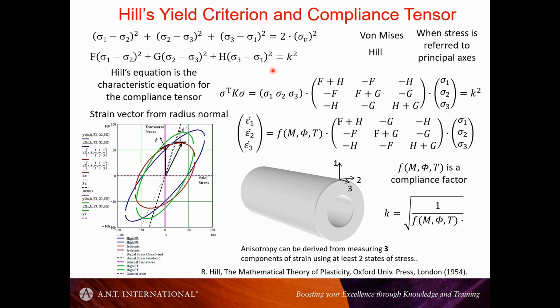A little bit more complicated when you get to zirconium alloys, because it's not so much a von Mises stress as an energy criteria. And Hill from the University of Bristol devised or reasoned that the point at which the material will yield, especially for an anisotropic material, is dictated by how much work you put in.